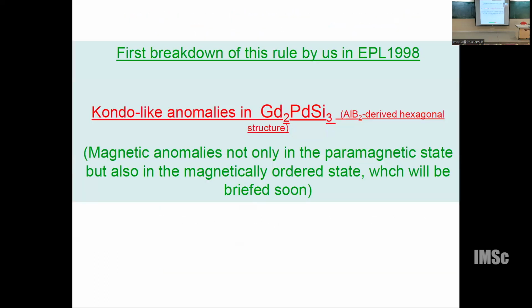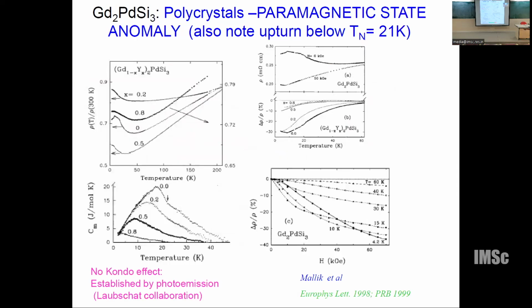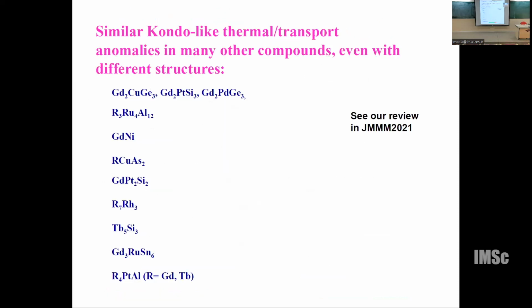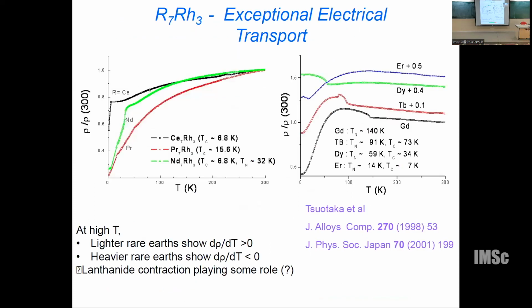And we reported that even in this compound, we see a resistivity minimum here. Even if diluted by yttrium, you still find it here. Even the heat capacity is quite large here. So it behaves like a cerium heavy fermion compound. However, it is not a heavy fermion. We can prove by other methods that it is not a heavy fermion. We found many other compounds in this family behaving similarly. And there is one set in the family where the temperature coefficient of resistivity is negative, where the minimum is somewhere here at high temperature. So even some of the heavy rare earth compounds, where you don't expect an anomaly, behave like cerium on the face of it.